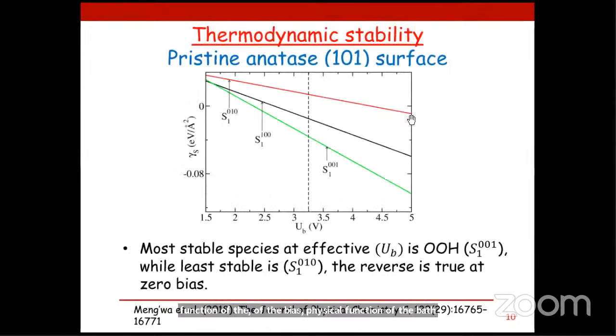So these are some of the results that we got. This is from the pristine anatase 101 surface. Basically, this one was just to give us a baseline comparison with what will happen with the coupled oxides. So if you look at what we have here, we see that